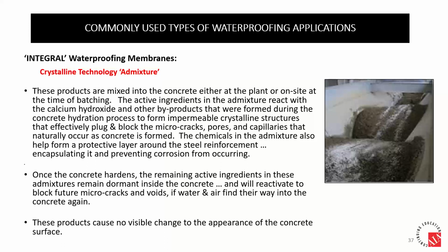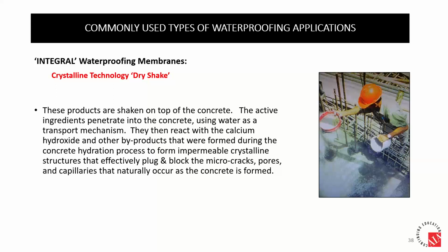In the picture is the crystalline material being mixed into the concrete before it's being poured. So as the concrete cures and hardens and forms these little air pockets and these little pores within it, those will fill with these little crystals. And that forms a waterproofing layer and protects the steel from water and from corrosion. But it's just like it sounds. Crystalline is like little shards of fiberglass, if you will. So it is a brittle approach.